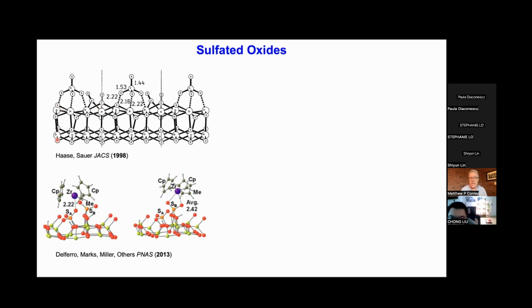However, if you take an organometallic and react it with a site that looks something like this, you've now introduced a completely different parameter into the game. Tobin Marks and Massimiliano Delferro have done a lot of really elegant work on this. This is a model of sulfated alumina, which is a bit different than the sulfated zirconia model I'm showing here. But what you can see is a zirconium coordinated to two Cp ligands, and there's a methyl group, and the zirconium is now interacting with a sulfate. The zirconium never interacts with the basic Al-O-Al bridges here for steric reasons. So essentially what you've done is create an ion-pairing environment for a cationic organometallic.